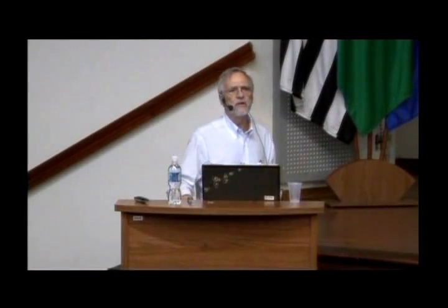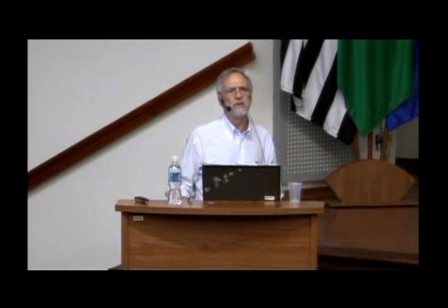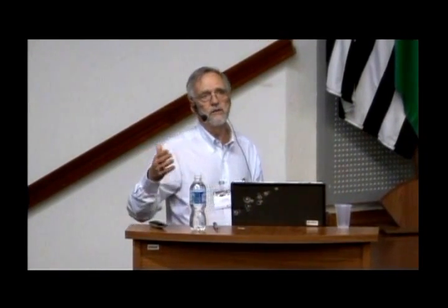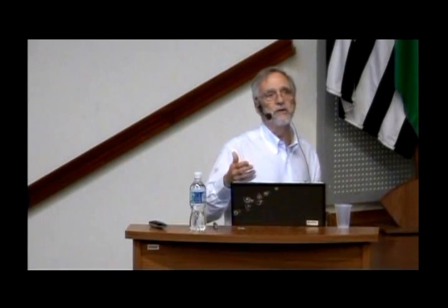Good talk, thank you. I guess I have a basic question. Why don't quantum dots photobleach? Are they protected from something, or what's the mechanism behind that? Because it's not a photochemical process. There are no chemical changes happening. You are simply getting essentially wavelength transformation. The quantum dot, after it has absorbed the light and re-emitted, is chemically unchanged, whereas with organic dyes you have the possibility of chemical change.